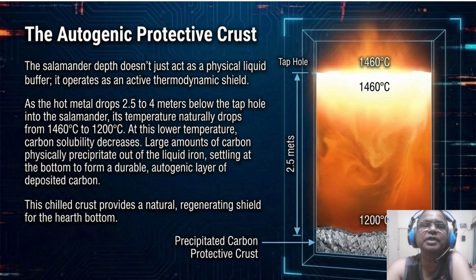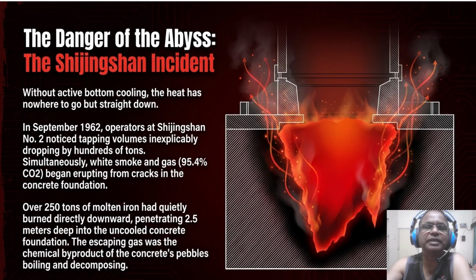So a large amount of carbon physically precipitates out of the liquid iron, settling at the bottom to form a durable regenerating layer of deposited carbon. This crust provides a natural shield for the hearth bottom. We are not just relying on the brick, we are using the chemistry of iron to grow a protective skin. However, if you lack active cooling below the crust, the heat will find its way out. So the danger of the abyss is shown by a different plant incident.